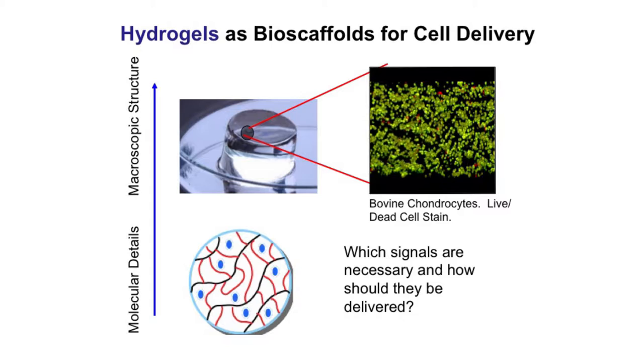There are many different scaffolds one can work with, so I'll just introduce you to one type — a hydrogel scaffold. If you could see the molecular level details, you'd see long macromolecular chains that would normally dissolve in water, but because of interactions between those chains, it renders them insoluble. Instead, these materials imbibe large amounts of water, and because of this, it imparts many properties that are similar to many of the soft tissues in our body.